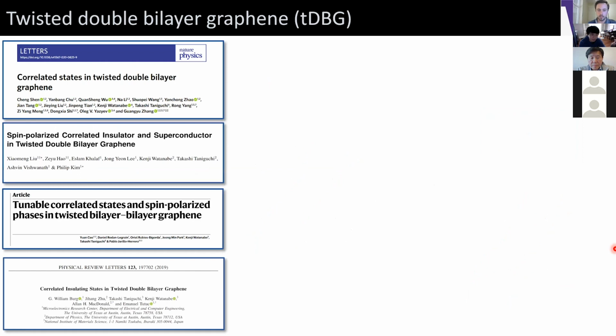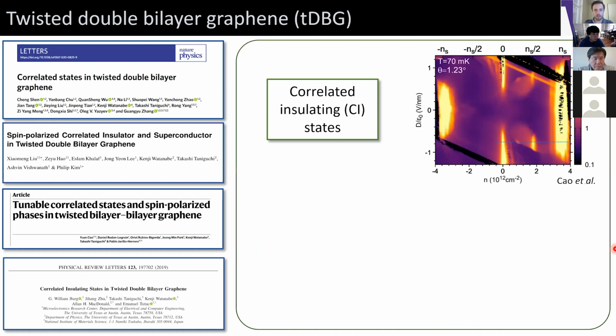And the system was characterized initially by 4 different groups about a year ago now, who all posted their papers, I think, on 4 consecutive days on the archive. And they all found some rough variant of the same phenomenological behavior, where when they measure the resistance in the color scale as a function of the doping and as a function of the electric field on the vertical axis, they see tunable single particle band gaps at the neutrality point and at full filling of the bands.